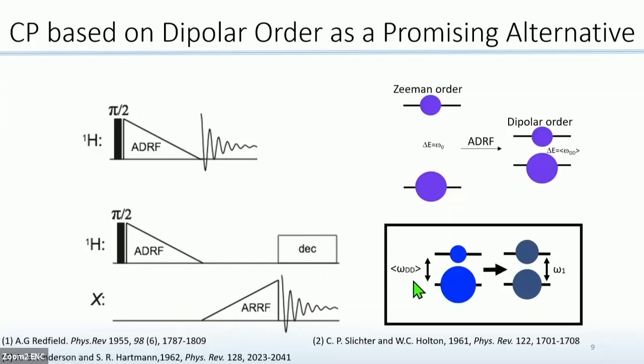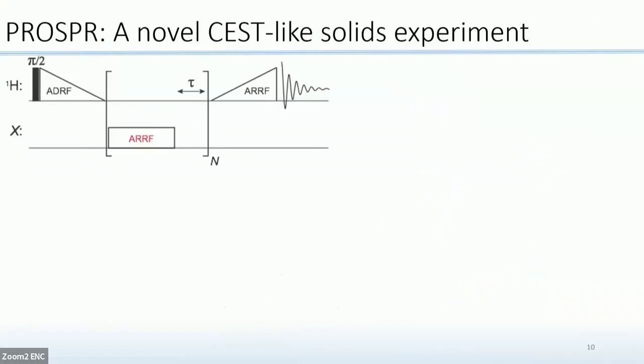And the matching conditions here are a bit different than Hartmann-Hahn CP. The matching conditions would be to the local dipolar fields of the protons. And the advantage of that is that, first of all, these matching conditions are very broad, so they're pretty flexible and forgiving. And also they're significantly lower power compared to Hartmann-Hahn CP. So this is the type of sequence that we came up with, and that's the sequence we termed PROSPR.